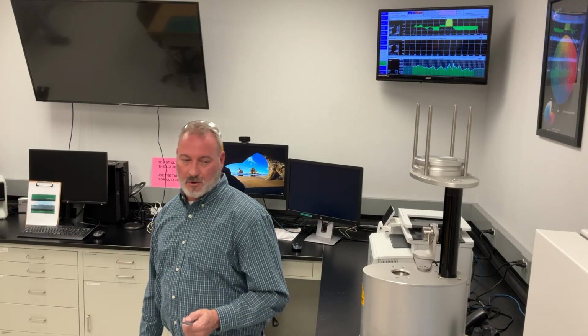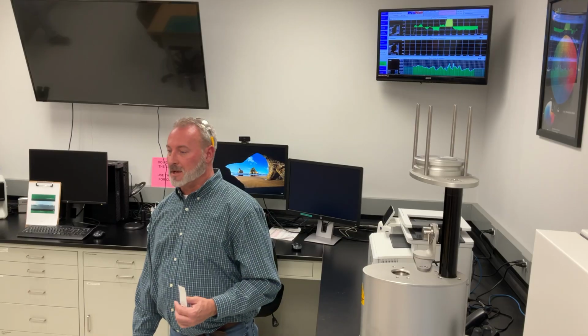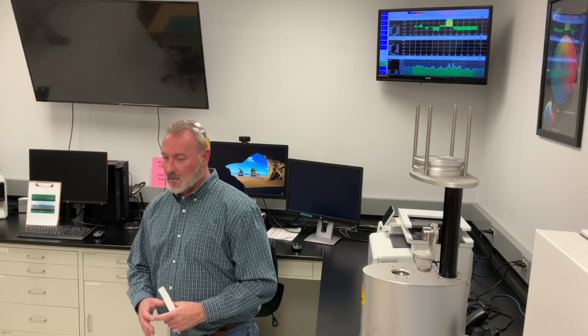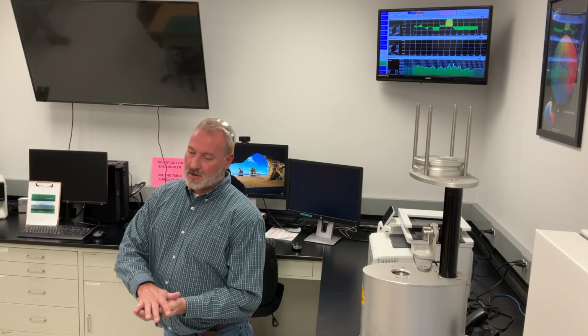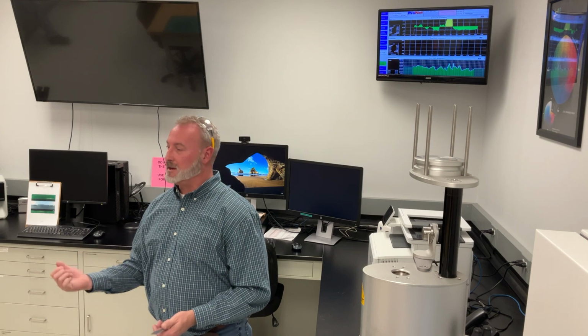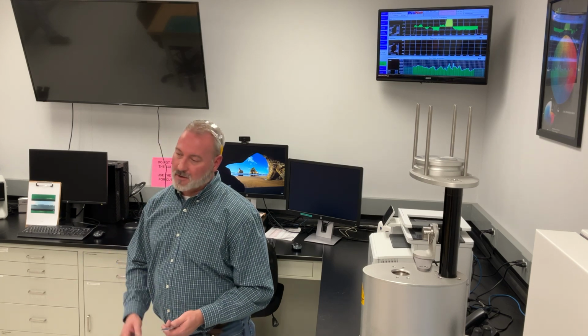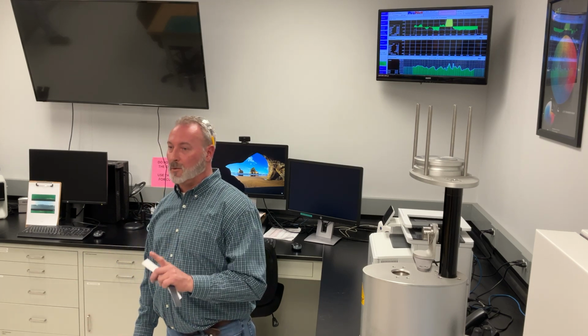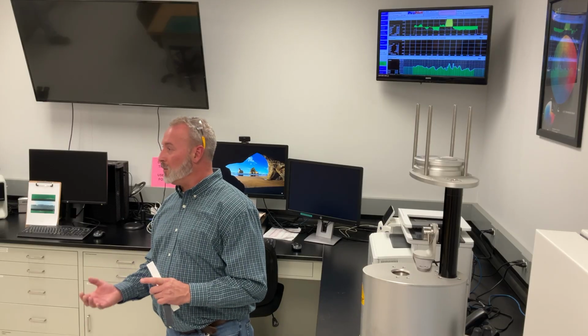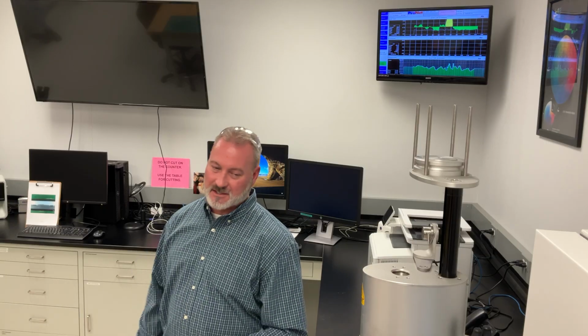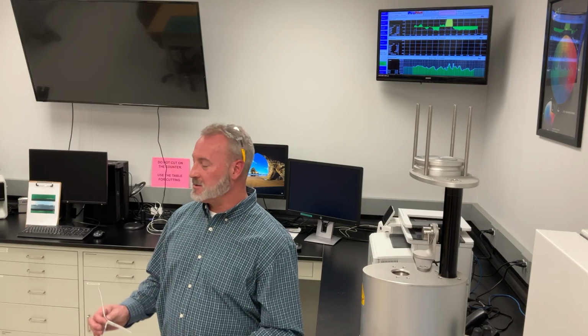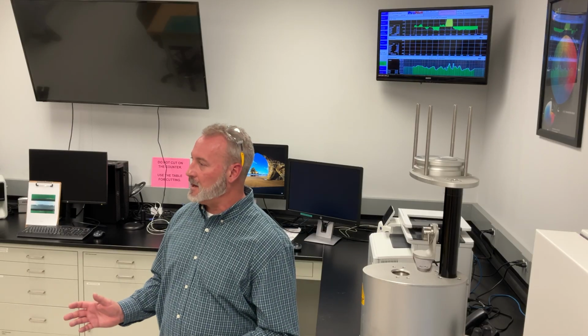We also do a water absorption test. We take a little disc, we weigh it, we put it in this little apparatus with some water on it, we stick it in an oven, we pull it out of the oven, we weigh it again, and it cannot gain more than 1% weight or pick up more water than that. When we first started doing that, we had a homemade apparatus, and we got some crazy numbers, but we finally tuned that in, and that's another one we don't fail.